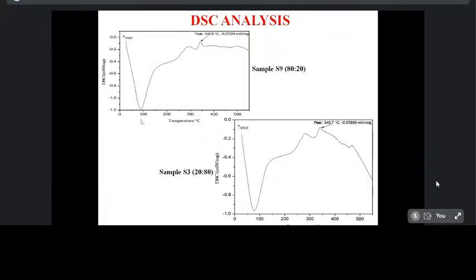The reaction becomes exothermic from the temperature of 225 degrees Celsius for the samples S9 and S3, due to the release of the energy of combustion of the organic matter. The distinct peaks were attained at the temperatures of 342.6 degrees Celsius and 340.7 degrees Celsius. The DSC curve is associated with the combustion of sorghum panicle and pearl millet, because the exothermic peaks were achieved as a result of releasing energy by the decomposition of fixed carbon and residual lignin.